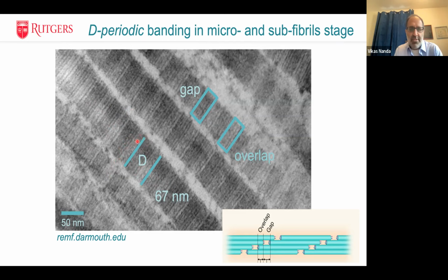And these gaps represent areas where there's either higher density of protein or lower density of protein. And you can see here, if you zoom in, the staggered assembly of individual collagen triple helices, and the gaps between them create these spaces where, in this case, for example, dye can come in and give you a darker stain. And regions that are lighter are completely filled with protein, so you don't get as much of the dye coming in and giving you that stain.